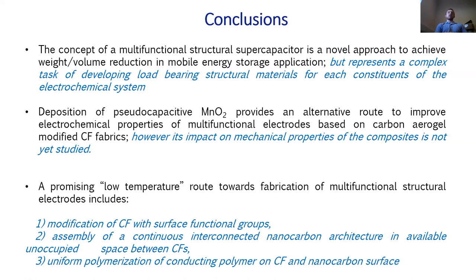And the last is, there are other ways to achieve a combination of high mechanical and chemical properties without going to high temperature for carbonization of our material. And one of these methods, which I'm working on, basically focuses on three steps: functionalization of carbon fibers, assembly of continuous 3D network of nanocarbons in the space between carbon fibers and on its surface, and polymerization of conducting polymers, both on the surface of carbon fibers and